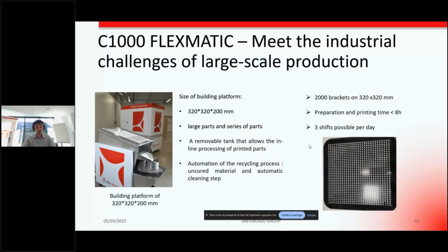A few quick words about the medium-sized machine, the C1000 Flexmatic. This machine was designed a few years ago with two targets in mind. Increase productivity, which is exactly what you can see on the right side of the slide. For instance, you can see 2000 orthodontic brackets printed on the 320 by 320 printing platform. Printing time for 2000 brackets is approximately 8 hours. So for a company running 24 hours per day, it's possible to print 6,000 parts per day. So it increases productivity and decreases production cost as well.